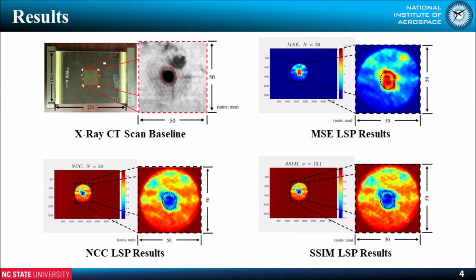On the top left, you can see the composite panel used in a baseline measurement using an X-ray CT scan, one of the more complicated methods mentioned earlier. The damage detected with this method is the dark spot in the center, outlined with the red dotted line. The other dark spots were just scanning artifacts and were ignored. The three remaining figures are results from LSP.